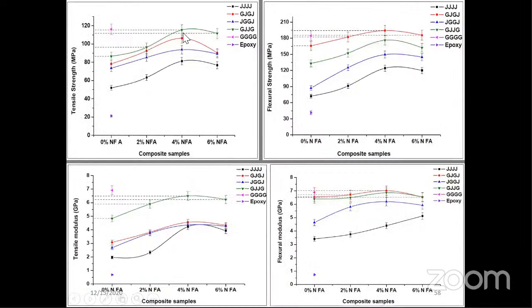So we went for nanotechnology again. In the nanotechnology, what we observed in this flexural strength, you can see, some materials with 4% nano fillers and with glass as outer layers and glass as a middle layer give better results when compared to the pure 4 glass composites. So glass as outer layers or as alternate layers with the 4% nano fillers gives the best results when compared to pure glass fiber composites. Then instead of pure glass fiber composites, 2 jute fibers plus 4% nano fillers can replace those materials.